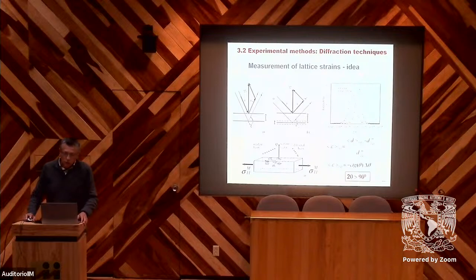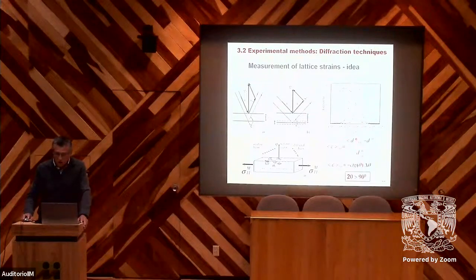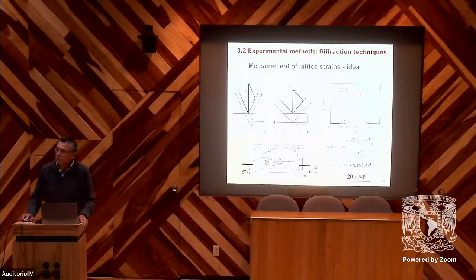So first, diffraction methods. Their basis is to measure the variation of d-spacing due to residual stresses. So we can consider that elastic strain is d minus initial d, divided by initial d. And in reality, using the diffraction method, this is measured by measuring the displacement of the diffraction peak. And to have a sensitive method, we need to use a Bragg angle close to 90 degrees.